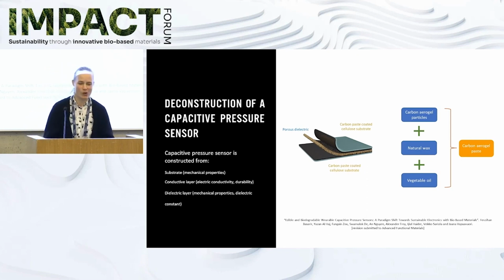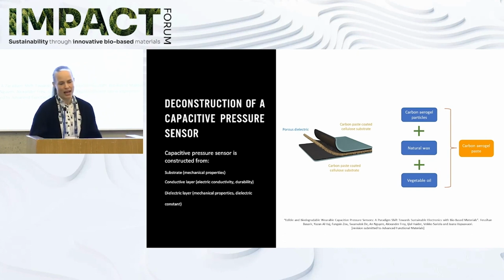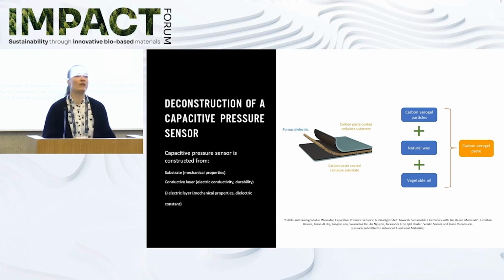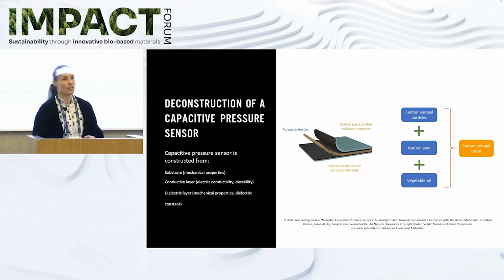So what we did here, our goal was not, again, just to use bio-based materials, but in addition to that, make the whole device biodegradable as well as edible. So we kind of limited the material choice based on these demands. And what we did here was that we made substrates out of cellulose nanofibers, and then we developed this type of conductive coating out of carbon aerogel particles, and then just edible natural wax and vegetable oil. And this worked pretty well. It's easy to spread on relatively rough CNF films.